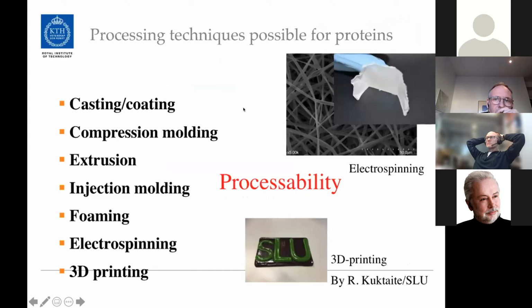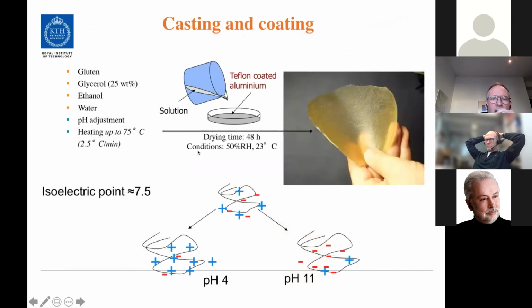For the proteins to be able to compete with fossil-based polymers, one has to be able to process them with conventional plastic processing techniques. But that's usually not really a problem if one knows the parameters for the processability. I will give some examples throughout. So casting, or if you coat paperboard, for example, with a dispersion of this material, you need to make it readily dispersible, and that you have to do by changing the pH of the material. Proteins have an isoelectric point, and at that point, the material is very difficult to dissolve or disperse. So you have to go up or down in pH, but then you can get very nice films and also coatings.